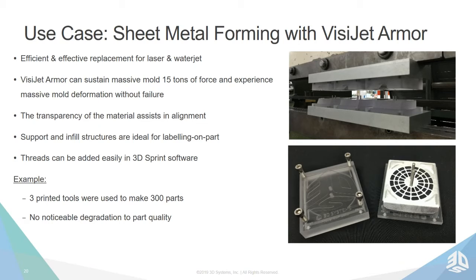Our tests show the 2-inch thick flat part of the armor material. This is one of the original engineering materials, not the HT90, but this is a great general purpose engineering material. You can subject this material to between 10 and 15 tons of force numerous times without fracturing. So the mold, and you see the mold here in the top diagram between those two metal plates, would always return to its true shape and could continue to be reused time after time in this particular case. So that's 10 to 15 tons of force being applied to the 3D printed part.